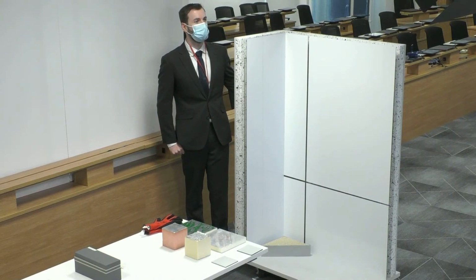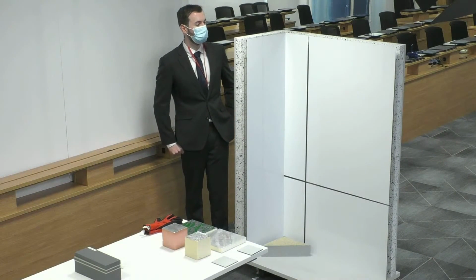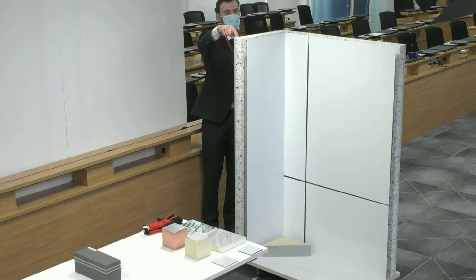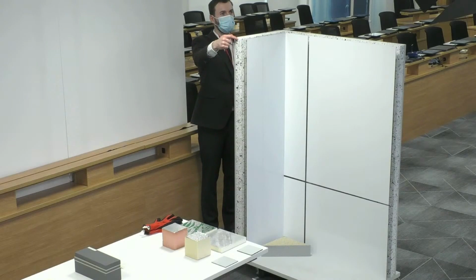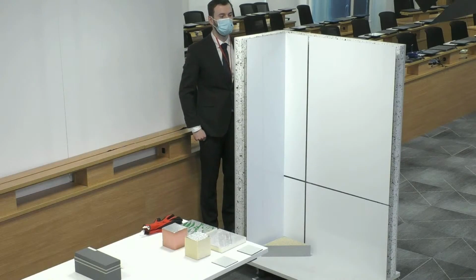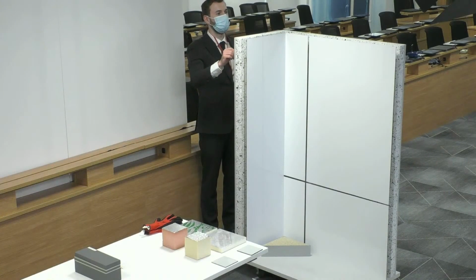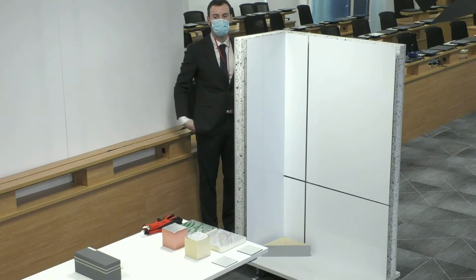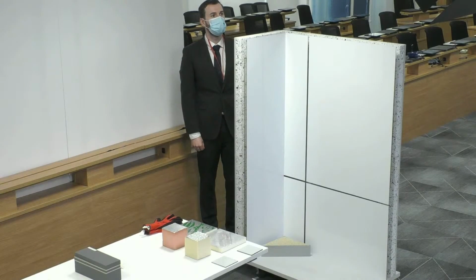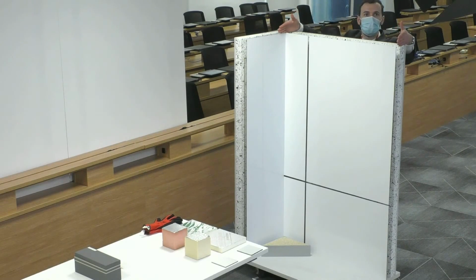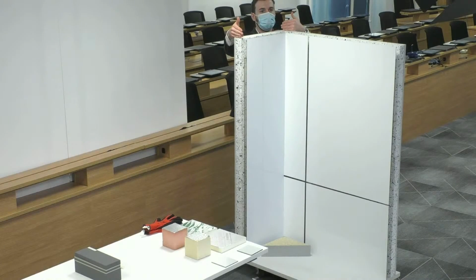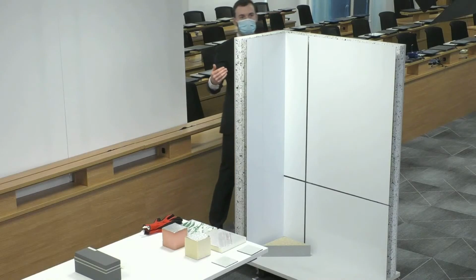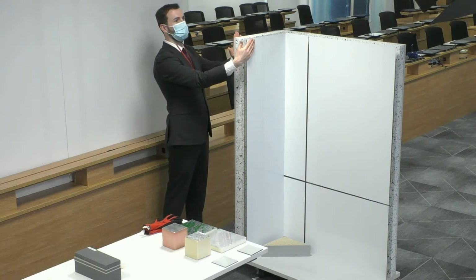The specimen holder is a metal frame with a calcium silicate board facing called the backing board. The specimen to be tested is then fixed onto the backing board according to the fixing conditions in the end-use application required. The specimen holder comprises 2 wings, designated a short and a long wing. It is the largest specimen used in any of the reaction to fire tests in either Europe or nationally. The long wing has a length of 1 metre and a height of 1.5 metres. The short wing has a height of 1.5 metres but a shorter length of 495 millimetres. The maximum depth or thickness of the total specimen tested in the single burning item test is 200 millimetres.